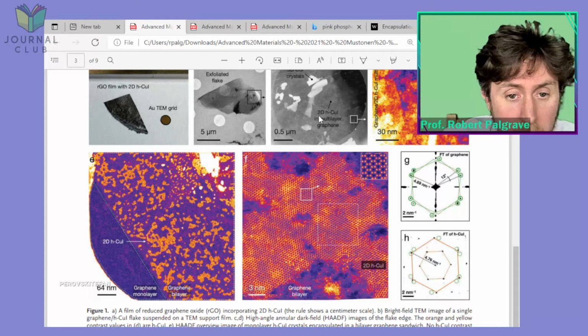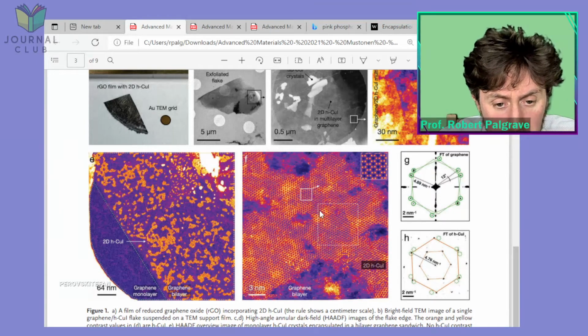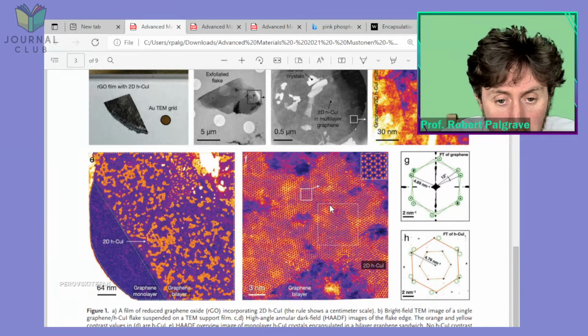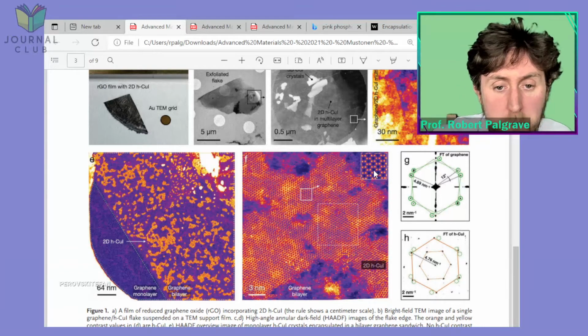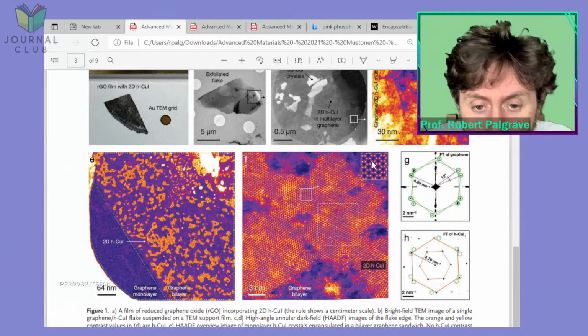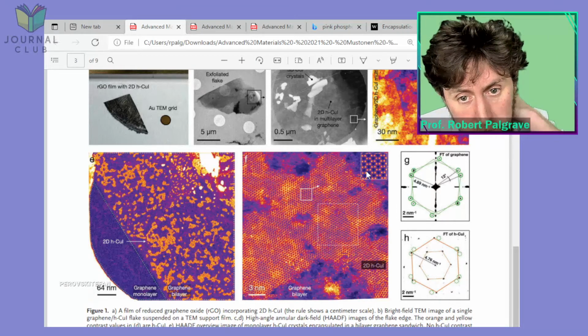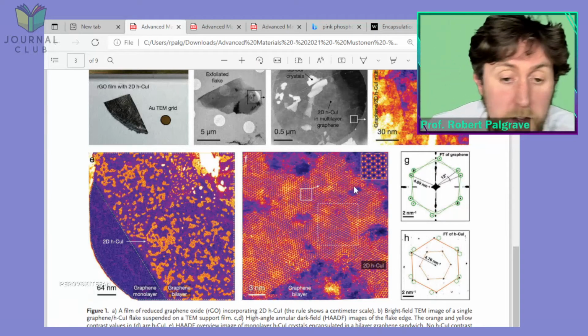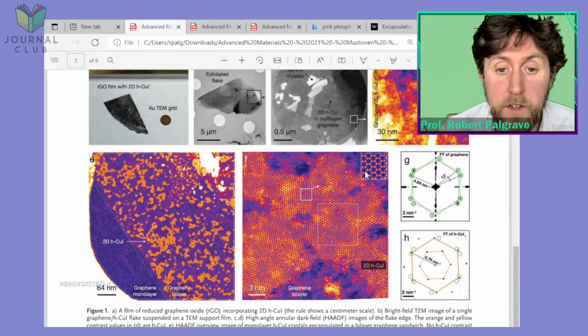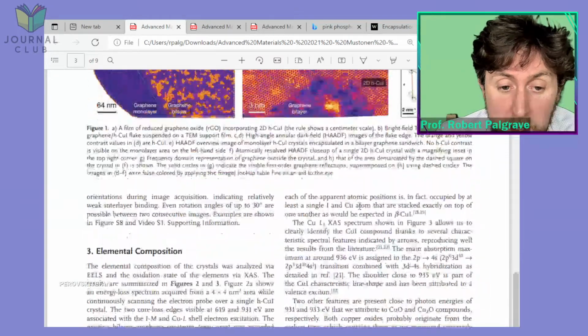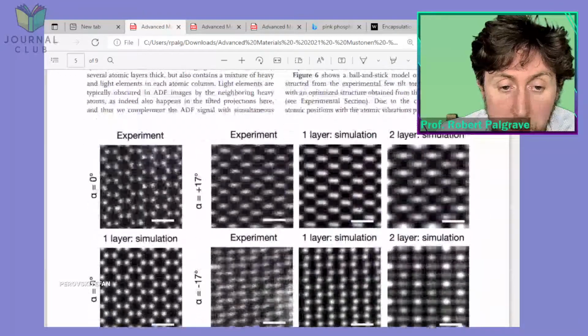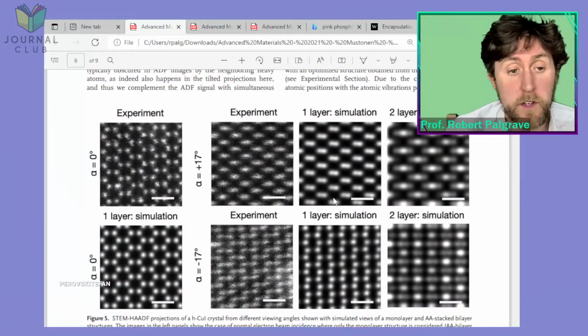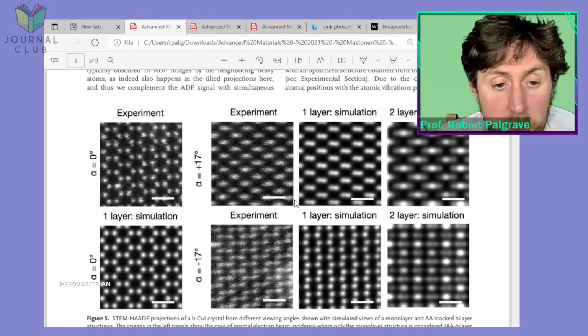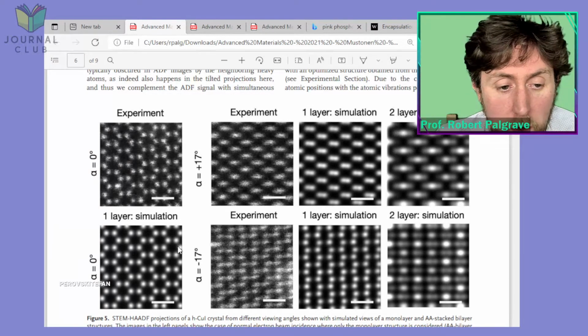Okay, so then we have some microscopic images. And you can, I think, see down here in the highest resolution, this scale bar is 3 nanometers, so it's pretty small, and you can see these regions are very strongly ordered, what's going to turn out to be cuprous iodide. So you can see this pattern here, we're actually getting atomic resolution, so we're actually seeing the individual atoms using transmission electron microscopy. So that's how powerful this technique is. We're seeing the individual atoms here, and as they're going to do later, they're going to compare the pattern of atoms with some simulations to prove beyond doubt, I think, in my opinion, that they have stabilized this phase.